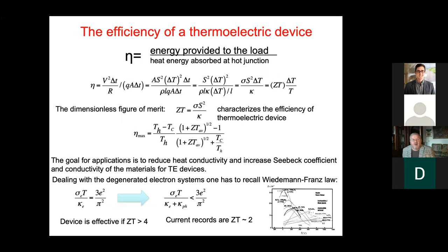So now I want to discuss what about the efficiency of a thermoelectric device. Efficiency is determined as the energy provided to the load divided by the heat energy absorbed at the hot junction. And it is expressed in terms of the so-called dimensionless figure of merit, ZT, which is equal to the conductivity of your sample multiplied by the square of the Seebeck coefficient divided by the heat conductivity.